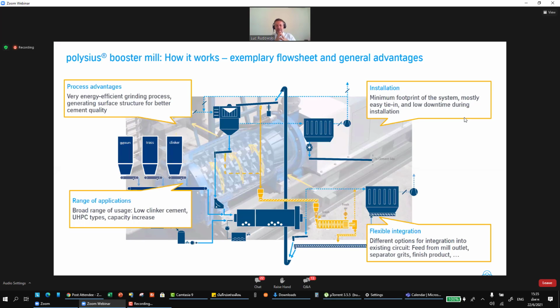And it's a kind of separate grinding, or a third chamber of a ball mill, whatever you want, a separate grinding. Because in fact, when you have limestone cement, for example, the clinker percentage within the separator reject is increased. So instead of 75% of clinker that you have in the cement, it's increased up to more than 85%, because it's harder than limestone that is already in the finished product. And then you can preferably work on grinding the clinker separately. That's the advantage of the machine, and that's the objective of reducing the clinker factor.